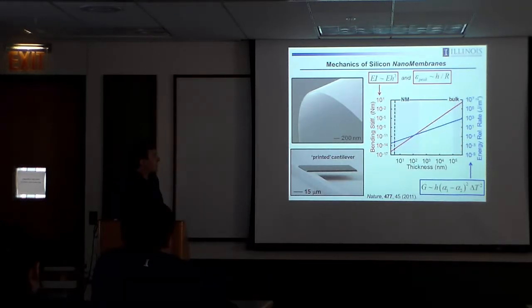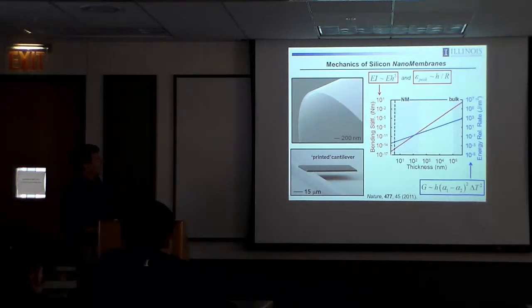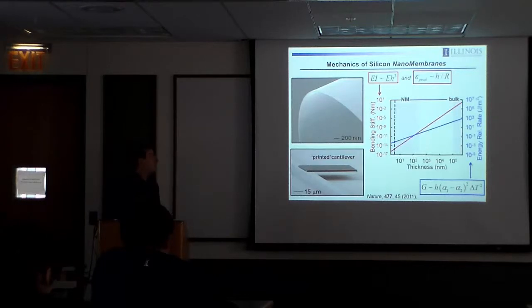But because of that cubic scaling, this is sort of a log-log plot, the bending stiffness decreases by many orders of magnitude as you reduce the thickness from a millimeter to, say, 10 or 100 nanometers. And so in this regime, the bending stiffness is maybe 10 femtonewton meters, and that's 15 orders of magnitude decrease in bending stiffness just through geometry control. And this is just linear elastic Newtonian mechanics, but that huge 15 order of magnitude change in bending stiffness has a qualitative impact on the way you think about the material. So it's no longer a rigid plate, but it's a thin floppy noodle.